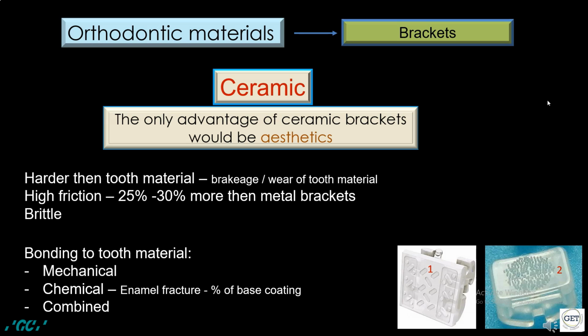Until today, some ceramic brackets are not easily debonded and might cause damage to the enamel surface. The removal might cause pain to the patient and the brackets might break, leaving a substantial part of the bracket bonded to the tooth surface. A coarse diamond burr is then required to remove those remains, with the risk of damaging the enamel surface. Some companies partially treat the pad to decrease the bonding strength, as seen in photo number 2.